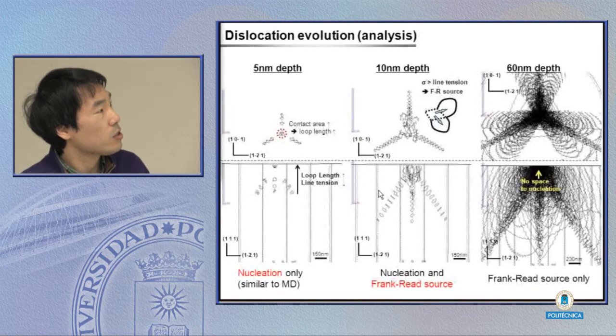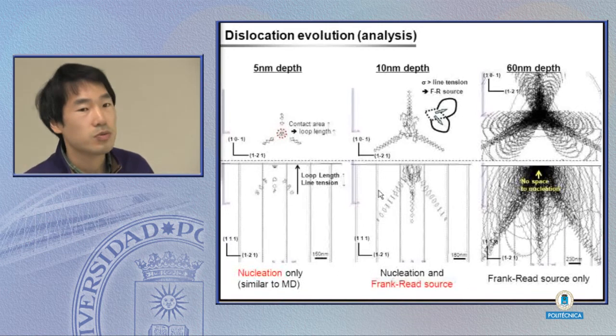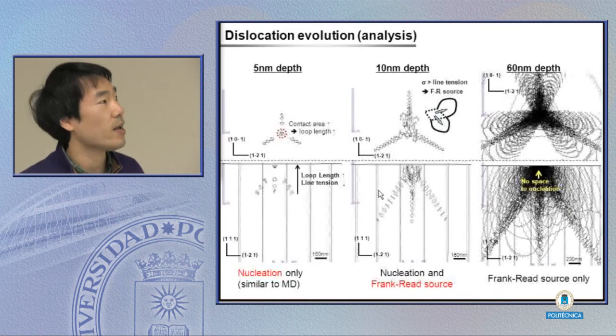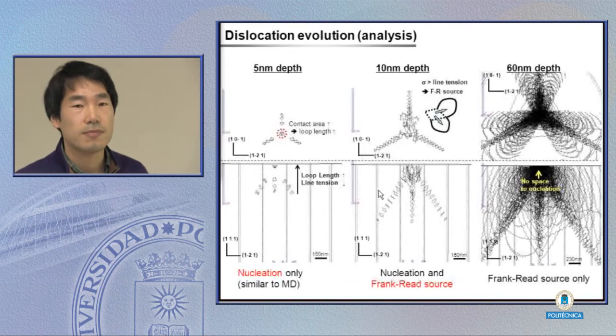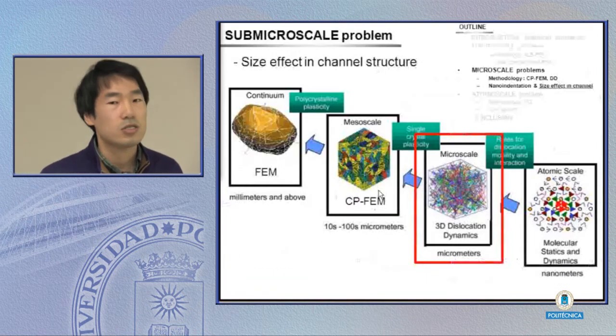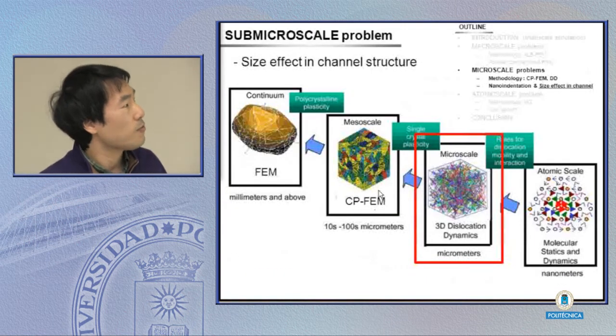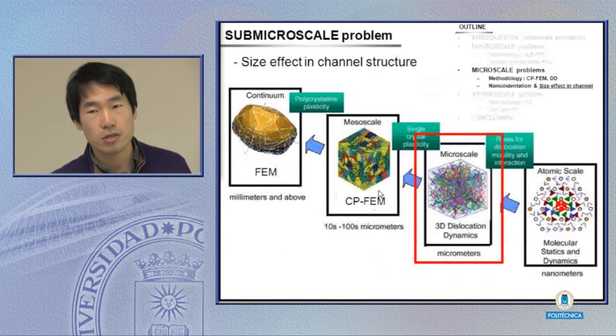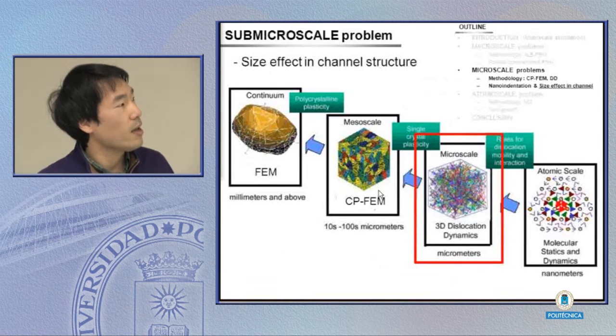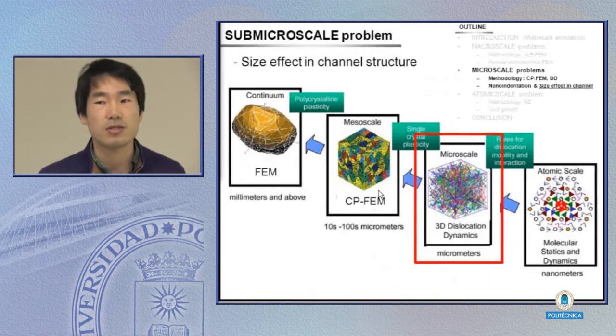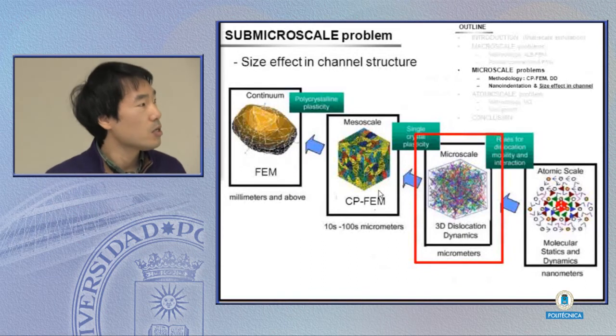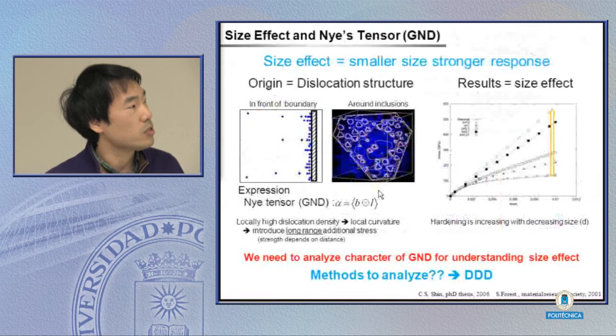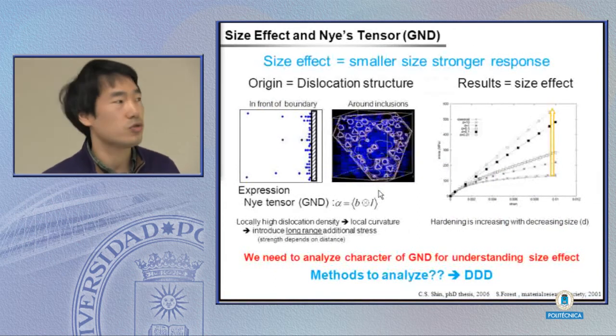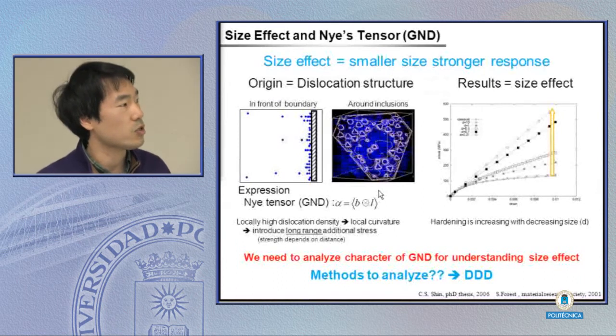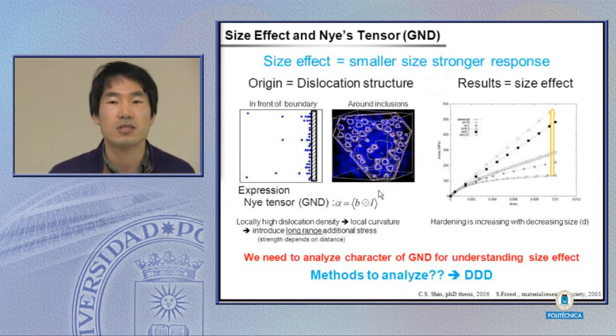So when the generated dislocation loop is large enough to act as the Frank-Read sources, dislocation can be generated both from the nucleation of the indenters of the dislocation and the generation by the Frank-Read sources. As soon as the dislocation density is too much to nucleate beneath the indenters, in that case, the dislocation is generated only by the Frank-Read sources.